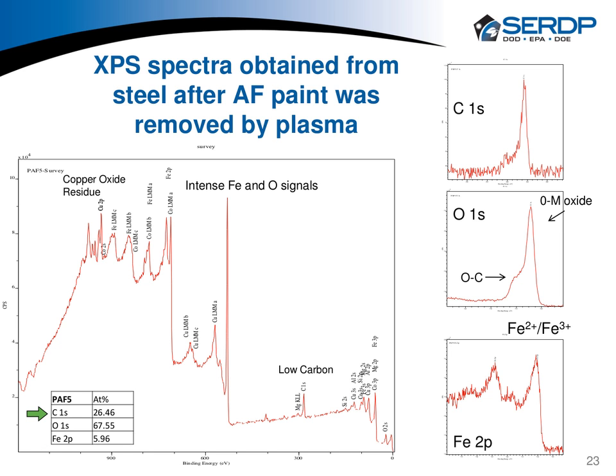Now, I have to say that with X-ray photoelectron spectroscopy and all the work that I've always done, from atmospherically exposed samples, I've never seen below about 15% carbon. And the reason for that is there's always adventitious carbon that gets absorbed onto a surface, especially a metallic, highly energetic surface for XPS. But if we look at the amount of iron and oxygen, it's pretty clear that there's, in this case, much less paint left on the sample than there was in the other case. And that is confirmed by looking at the oxygen region, wherein here the oxygen bound to carbon is much, much less in relation to the oxygen bound to the metal.